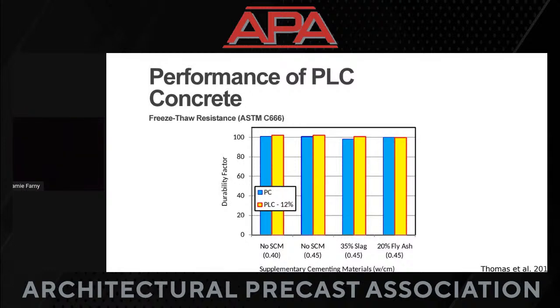That's the message there. I said I'm not really covering freeze-thaw. I can point you towards some information if you want to follow up on freeze-thaw, de-icer scaling resistance, but I am talking about freeze-thaw, where we've got in this set of materials, the blue bars are Portland cement, the yellow are a 12% Portland limestone cement mixture. So 12% limestone in the PLC. So this is a durability factor where we expose this sample to freezing and thawing in water or air, and we cycle it. And you want to get 300 cycles usually.